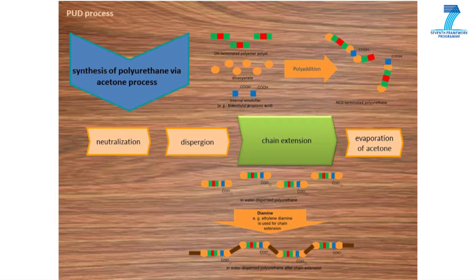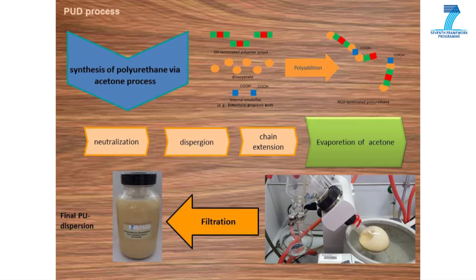The NCO-terminated polyurethane chains are connected by the addition of diamine chain extender, which results in further growth of chain length. The removal of acetone is reached at a rotary evaporator. Acetone is removed at reduced pressure and filtered afterwards.